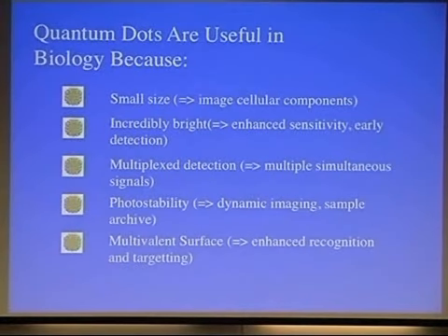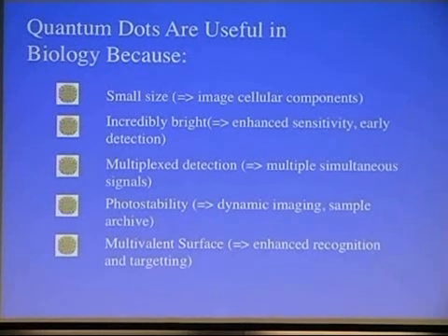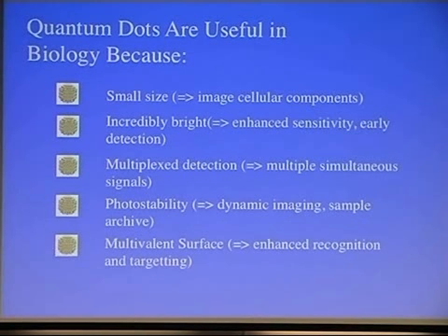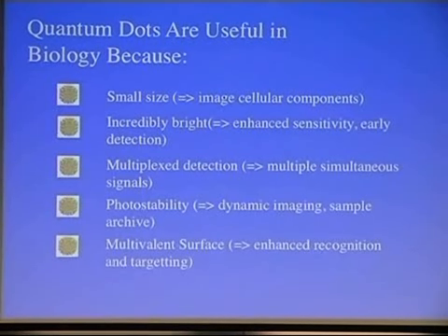Also, because they're inorganic, they don't photobleach, which means that usually organic molecules, when you shine light on them, eventually do chemistry and they degrade. These inorganic guys don't. They stay bright all the time, which means that you can make a movie. And I'll show you a movie.